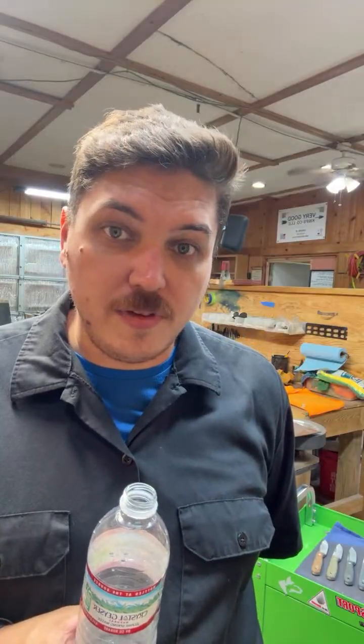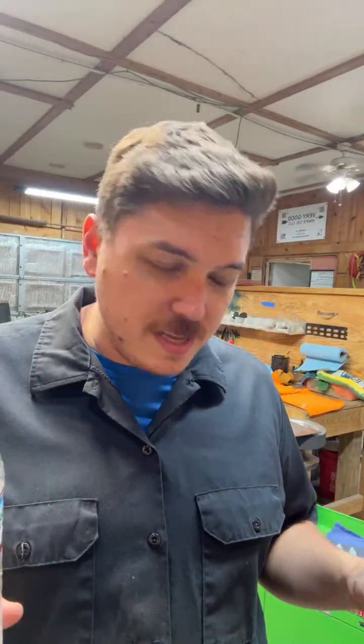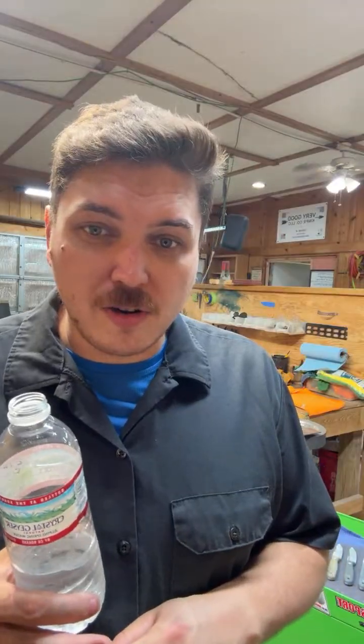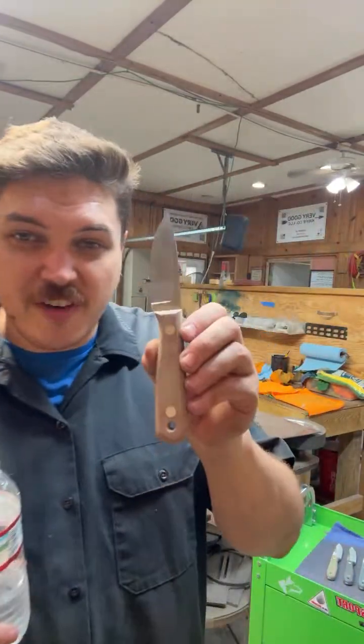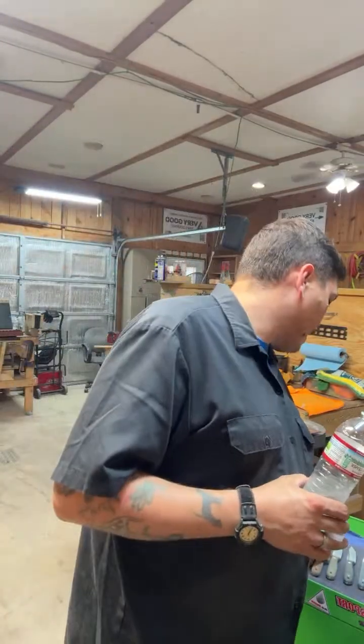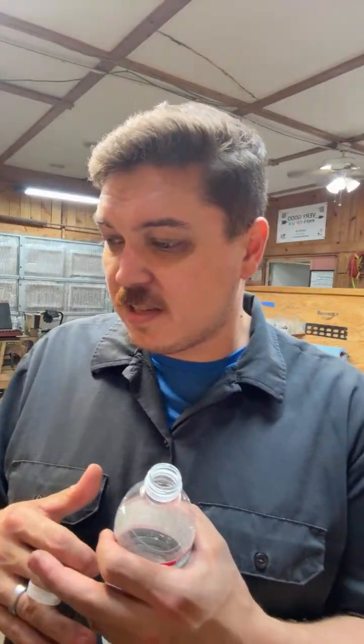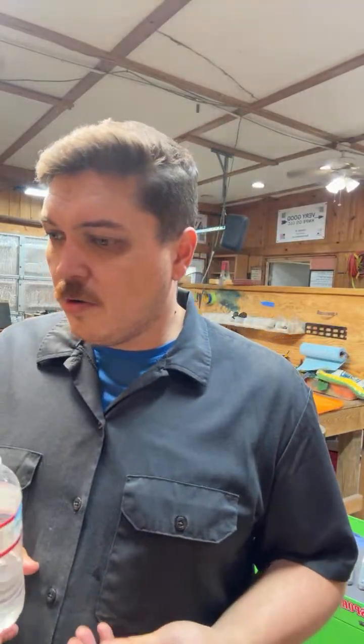If you're plate quenching, then all your grinding's got to be done after heat treat. At least I do all of my grinding after heat treat with Nitro V. Now, the difference between rough grinding a completely flat bar of steel at 62 Rockwell and grinding a flat bar of steel at like 55 pre-heat treat is night and day. And it's so night and day. If you watch enough of these live streams, you'll get to see it. You will get to see it. And like Steven and Zach and Fed Harrison and a lot of these guys that have been in here today, they've watched a lot of these live streams. They know the difference in belt consumption that I go through.